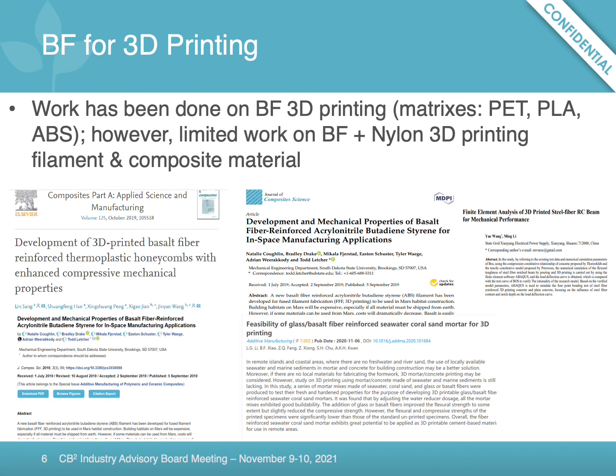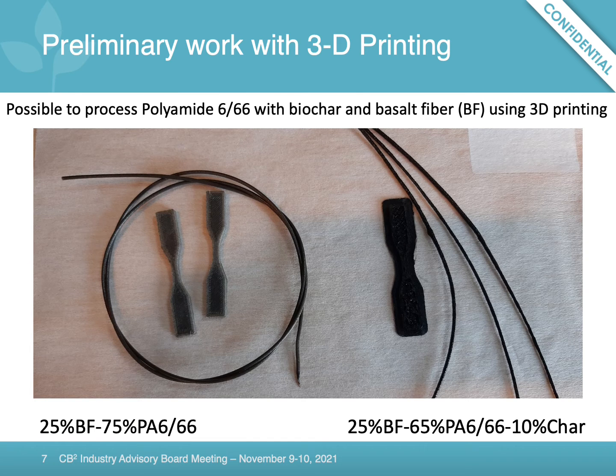Additionally, what we found in regards to use of basalt fiber for 3D printing was that it was used with other resins such as PET, PLA, and ABS. However, there was very limited work done on use of basalt fiber with nylon to produce filament for 3D printing. Therefore, we conducted some preliminary work with 3D printing to show that it is possible to process polyamide with biochar and basalt fiber using 3D printing.